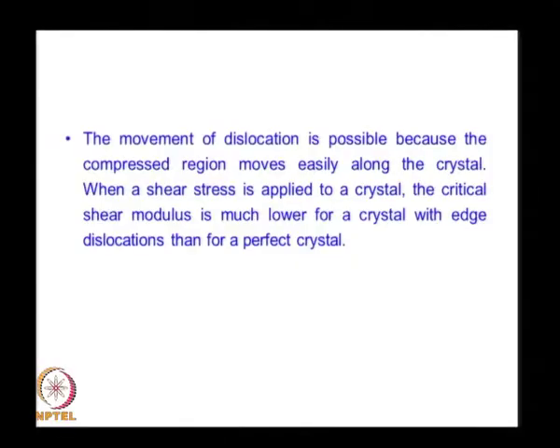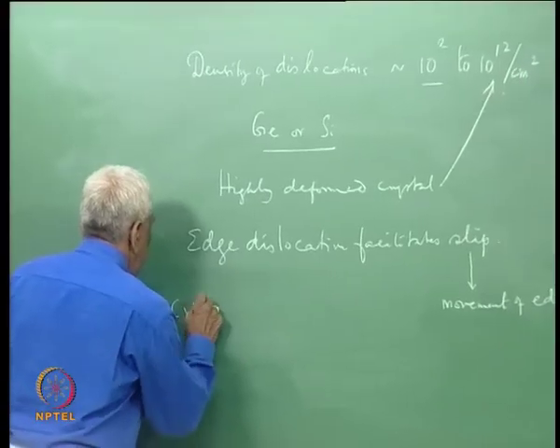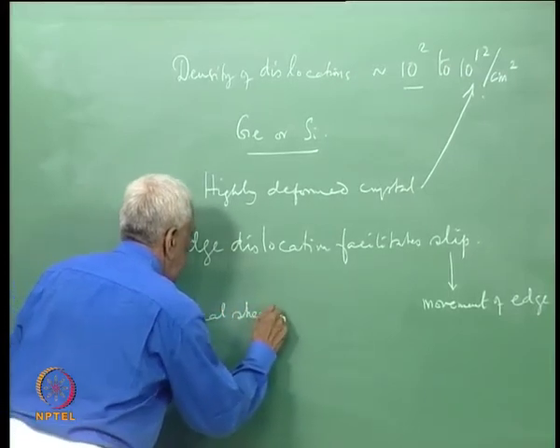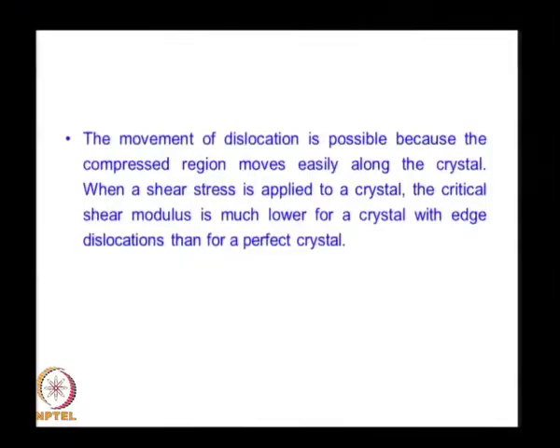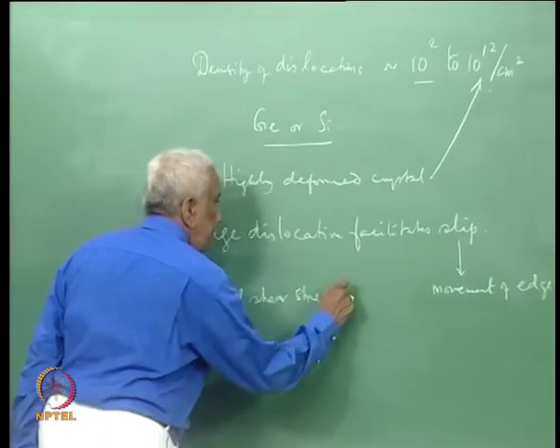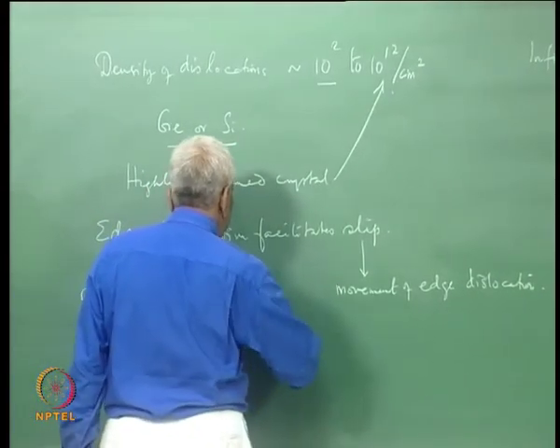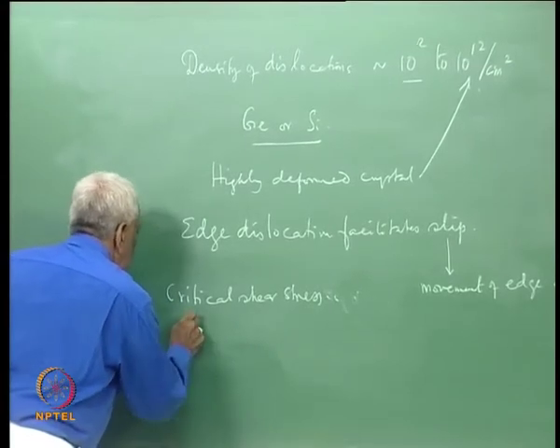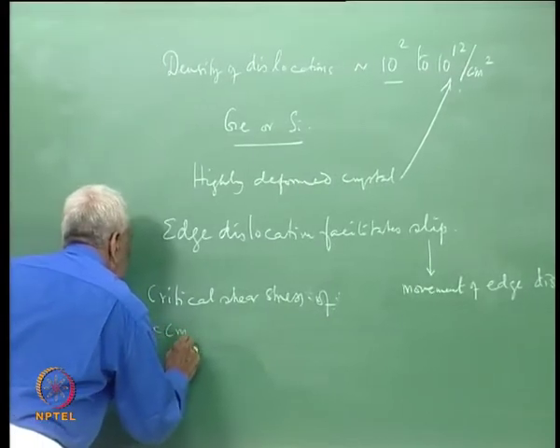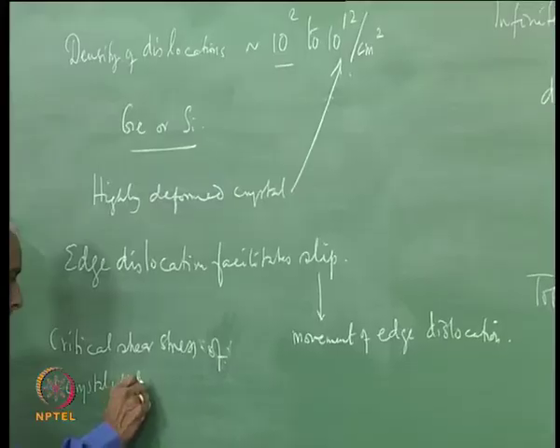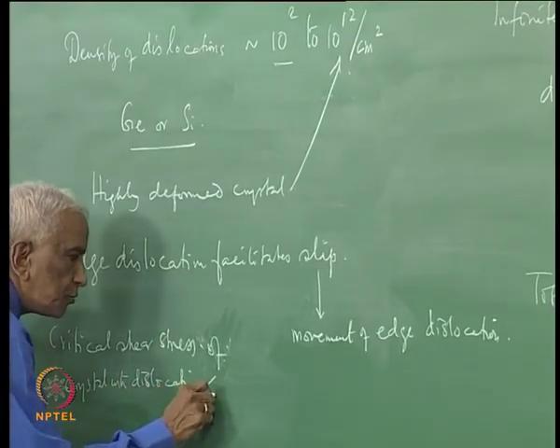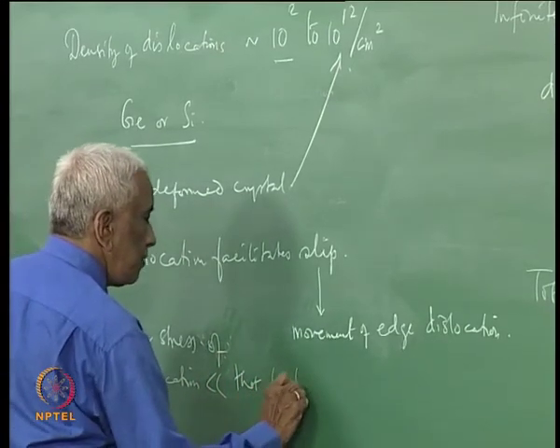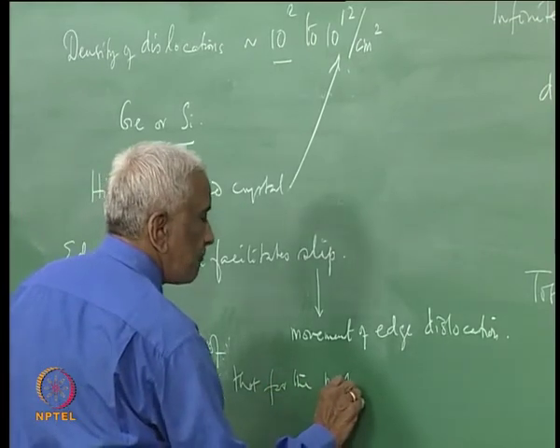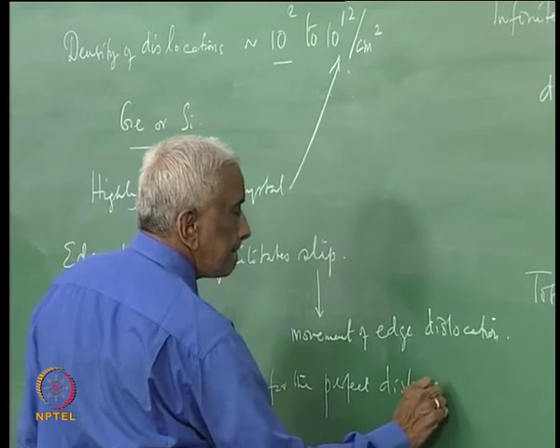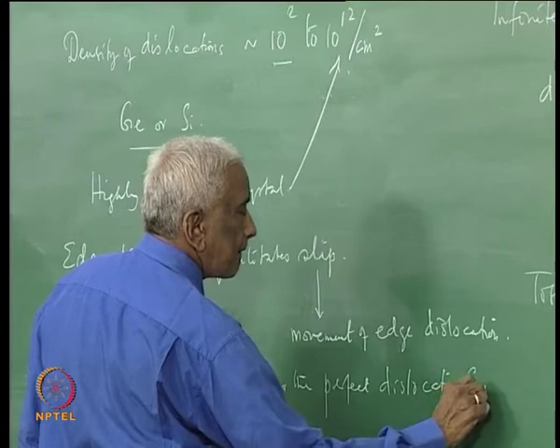When a shear stress is applied, the critical shear stress is the stress that is required in order to facilitate such a movement, and this is much lower for a crystal with dislocation, much smaller than that for the perfect dislocation free crystal.